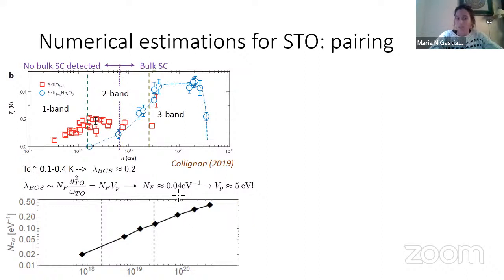You put in the numbers, and the pairing interaction that one would need from any weak coupling mechanism, whether it's coming from one phonon, another, or anything else, should be of the order of 5, 6, even here could be 10 eV. That's an extremely large interaction, in particular if it's going to come from electron-phonon coupling. So this is just something that I wanted to point out.